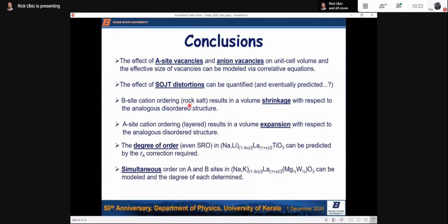B-site cation ordering, rock salt ordering, results in volume shrinkage with respect to the disordered structure. The A-site cation ordering, which is a layered ordering, results in a volume expansion with respect to the disordered form. The degree of order, even short-range order, in this stuff can be predicted by the RA correction required. And even simultaneous order on A and B sites can be modeled and the degree of each determined.